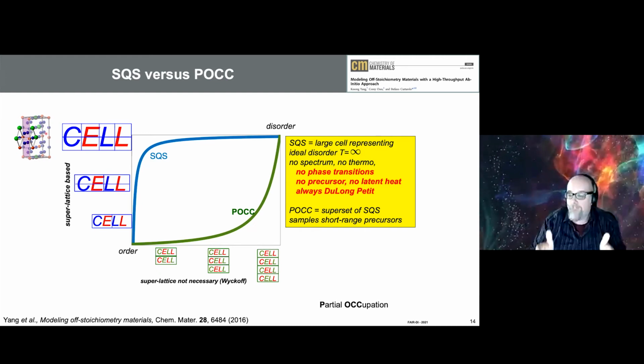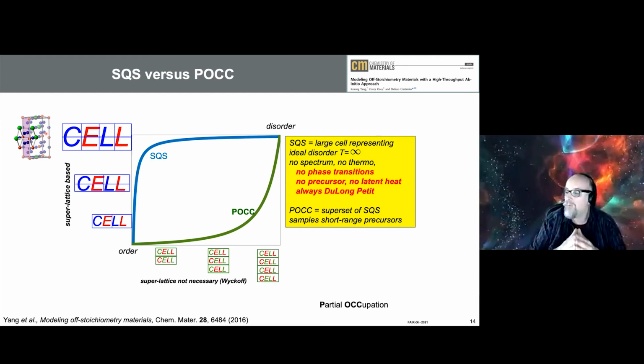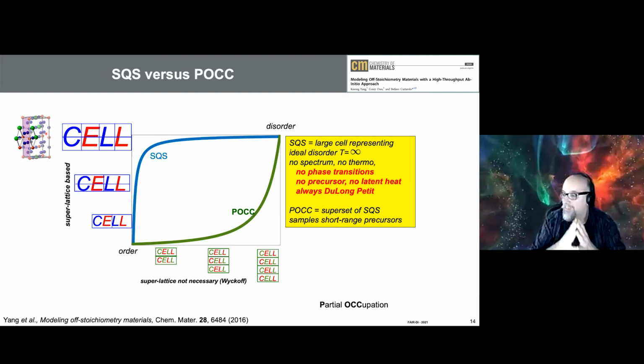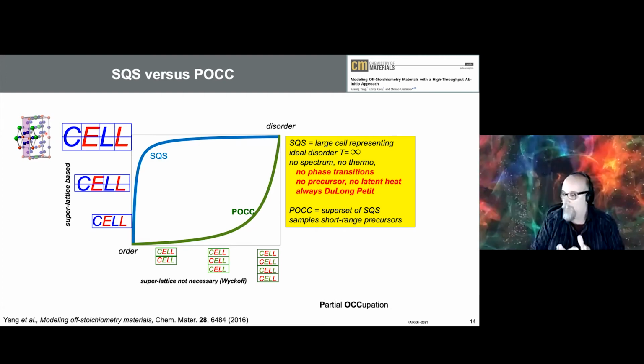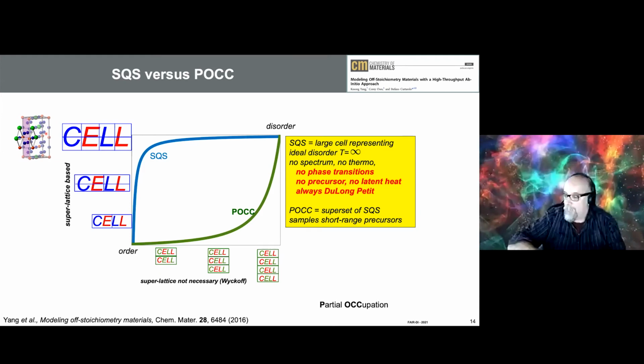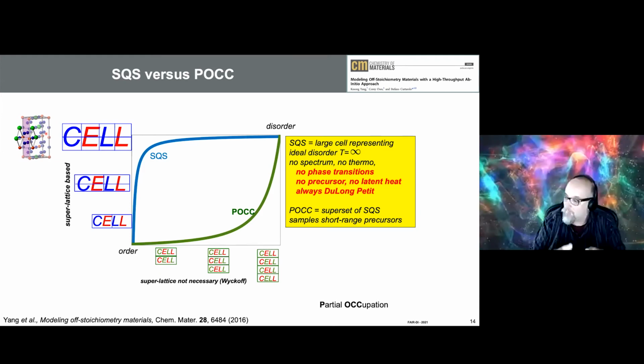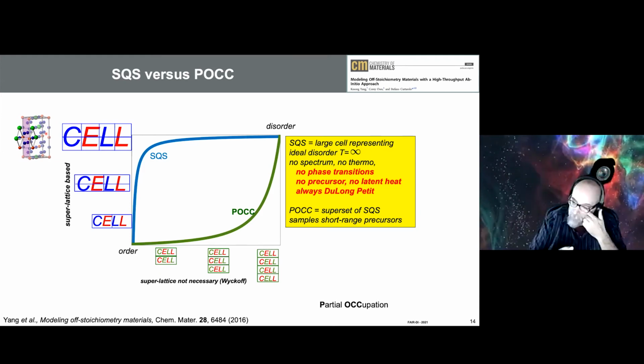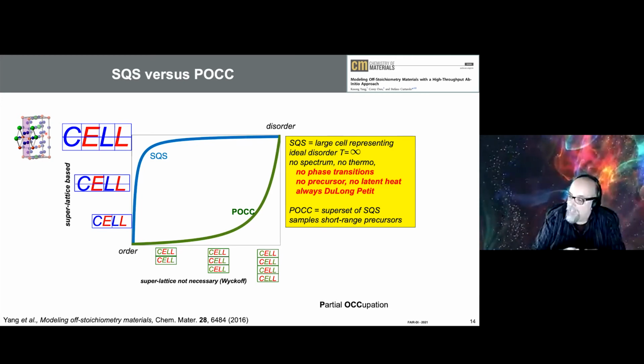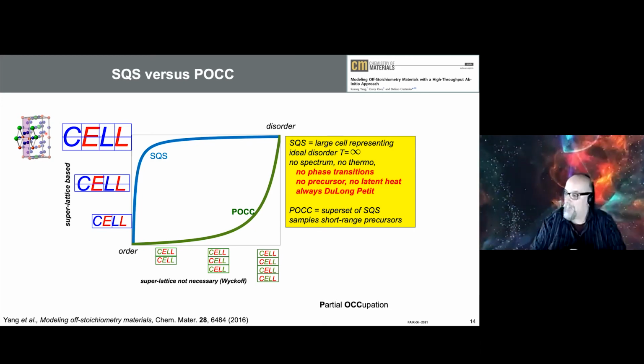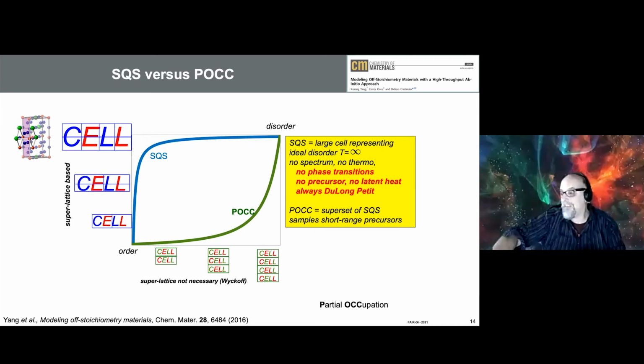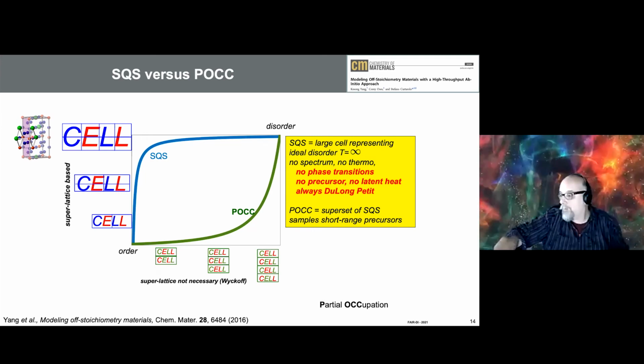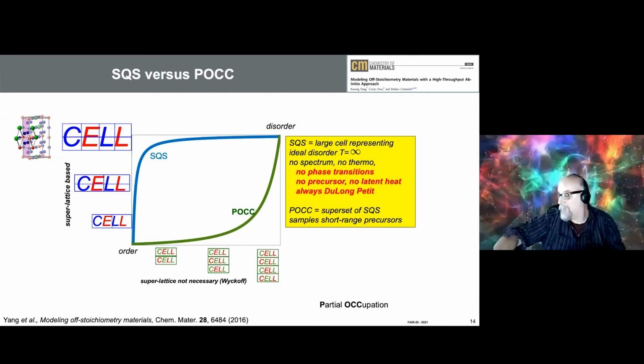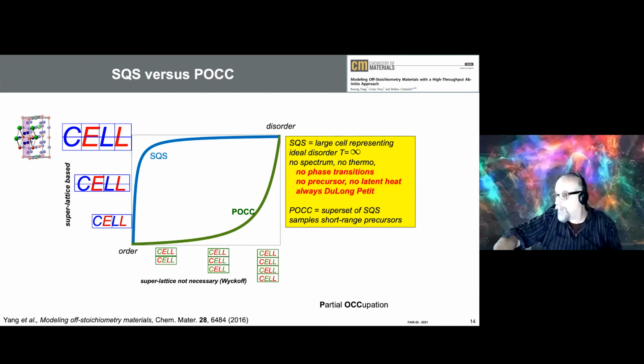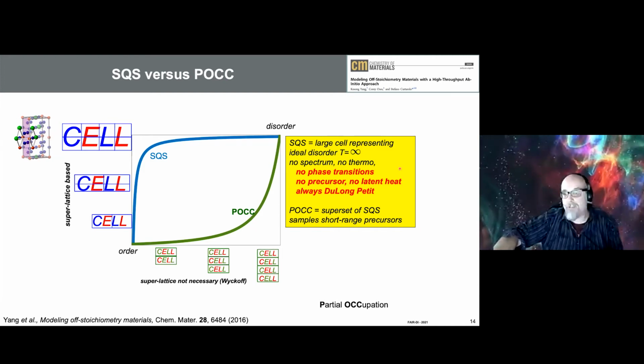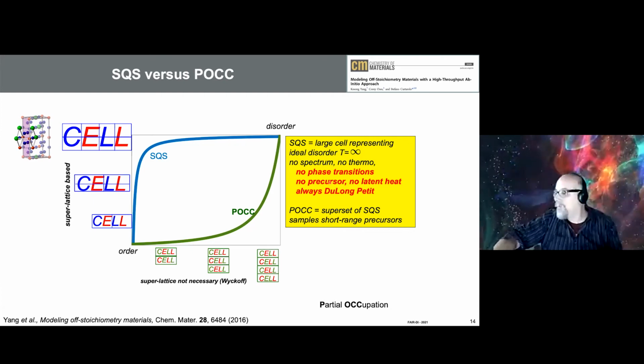SQS is the perfect method to study isomorphous disorder, silicon germanium, where everything is pretty much the same. But if you reduce the temperature, you start seeing the precursors when you hit the miscibility gap. And therefore these things do not have a spectrum, because all the enthalpies are pretty much the same, the enthalpies of the disorder, and therefore there is no entropy. The only entropy you can get from SQS is from the Dulong-Petit formula.